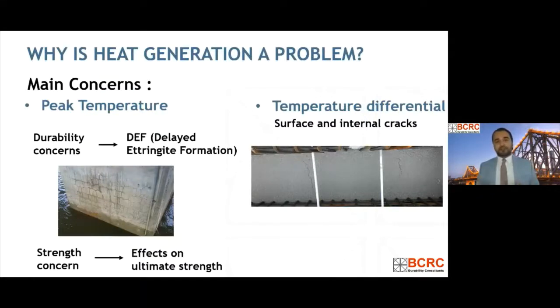The main concerns with the heat generation in concrete are peak temperature and the temperature differential, right? When the concrete is poured, the heat of hydration process starts, and it's an exothermic reaction, which means a lot of heat is evolved. So a lot of standards and specifications have a limit on the peak temperature, which is normally from 70 to 75 degrees. If the concrete is cured at a higher temperature than that limit, whether due to heat curing or due to heat of hydration, then we have some serious durability concerns, which are mainly due to delayed ettringite formation, right?